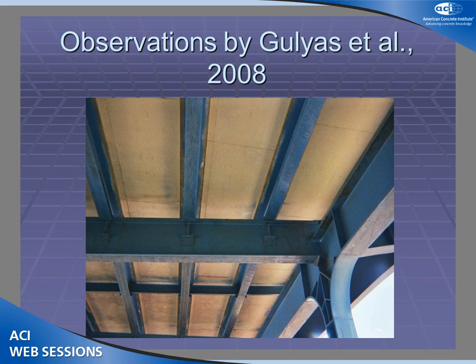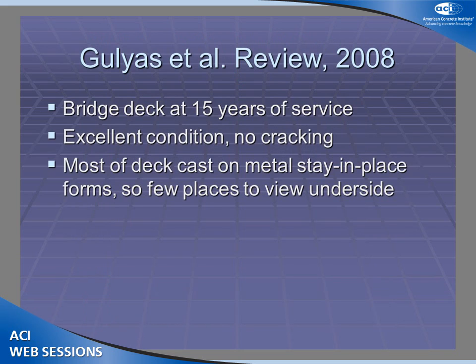Bob Gulyas took this photo of the underside of the bridge and reported on that in his paper in 2008. At that point, the bridge deck had been in service for about 15 years. Let me point out one thing about the location of this bridge. The greater Cleveland area has a wonderful combination of lots of bridges and some really nasty climate conditions in freeze-thaw. If you want a place to do bridge durability experiments, you can hardly come up with a better place than Cleveland. And this particular bridge is actually pretty close to Lake Erie, and so we get a lot of the storms that blow in off of there.